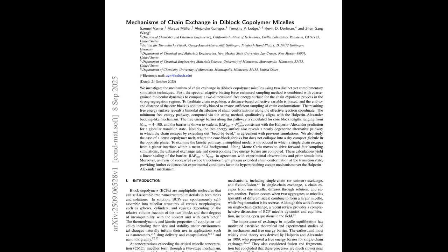They also implement kinetic Monte Carlo and forward flux sampling methods to estimate free energy barriers and escape rates under various conditions. By blending multiple computational strategies, the study aims to clarify the molecular pathways and energetic costs for chain exchange in Diblock Copolymer Micelles, providing a more detailed mechanistic understanding of this fundamental phenomenon.